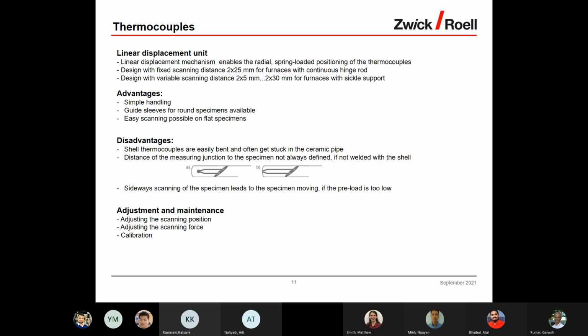The advantages: simple handling, guides available for round specimen, and easy scanning possible on flat specimen. The disadvantages: sheath thermocouples are easily bent and often get stuck in the ceramic pipe. The distance of the measuring junction to the specimen is not defined if not welded with the sheath. Sideways scanning of the specimen leads to the specimen moving if the preload is too low. And the adjustment and maintenance: adjusting the scanning position, adjusting the scanning force, and calibration.